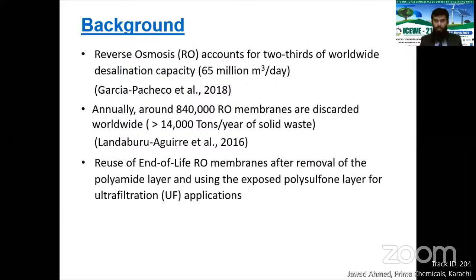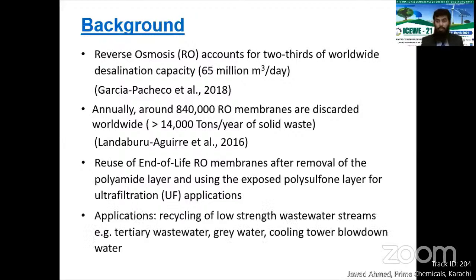One of the most attractive propositions that has been considered is to use these discarded RO membranes as ultrafiltration membranes after removing the active polyamide layer through oxidation and exposing the underlying polysulfone layer, which is automatically in the ultrafiltration range. So a whole new lot of possibilities spring up for the application of these recycled membranes, which are basically everything in the ultrafiltration spectrum.